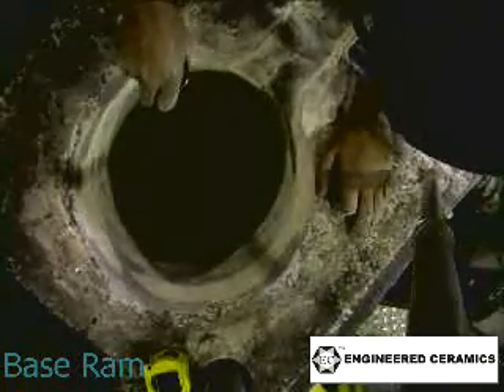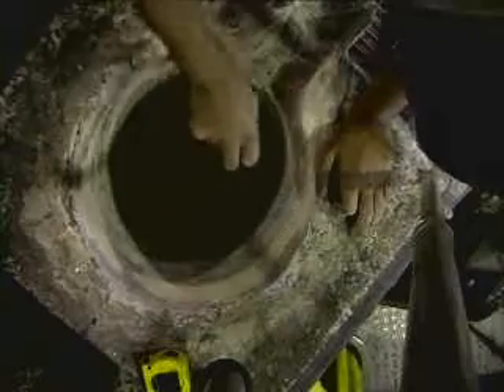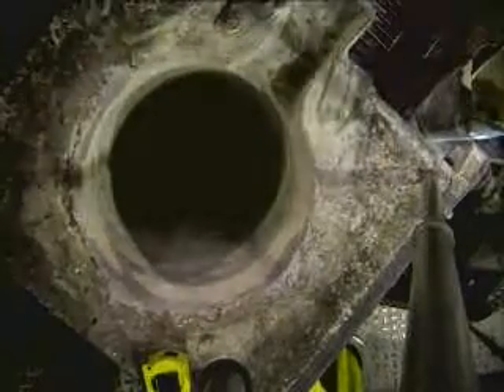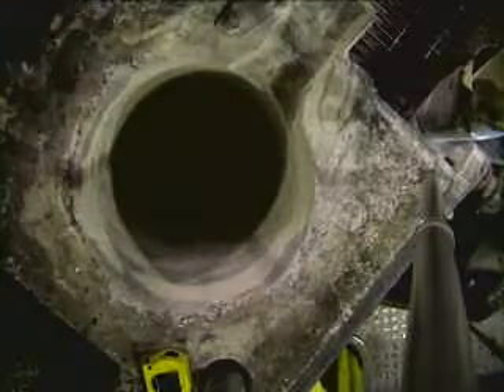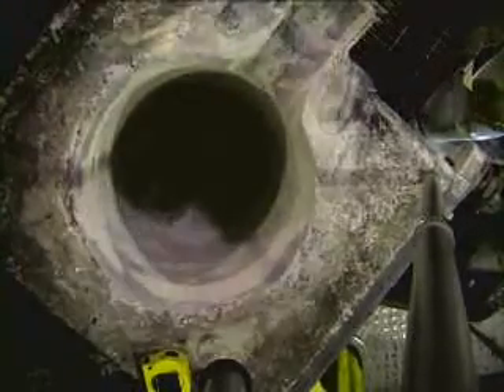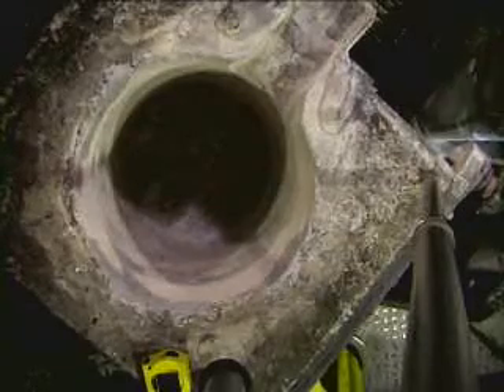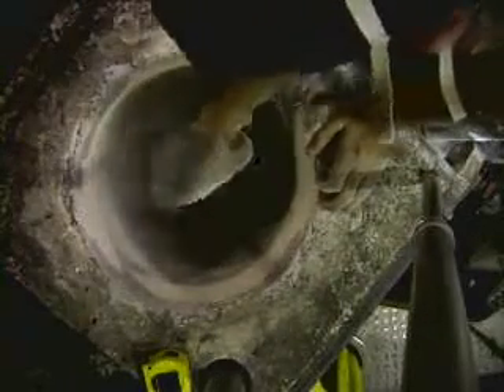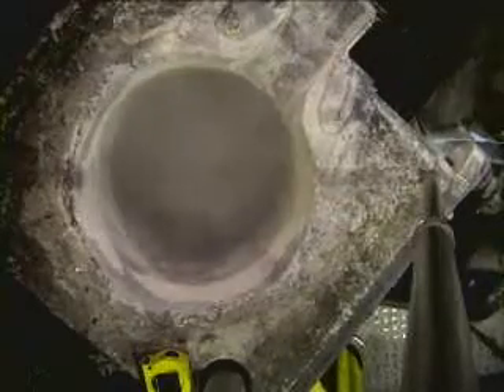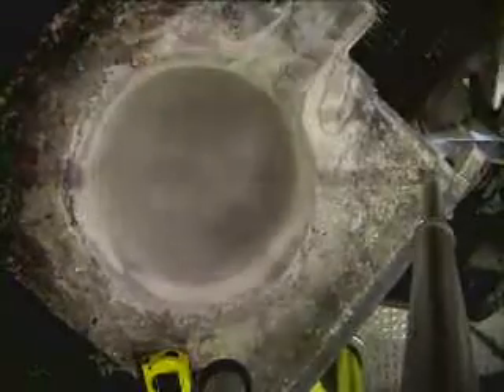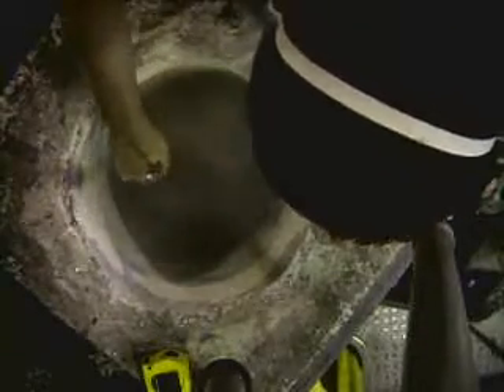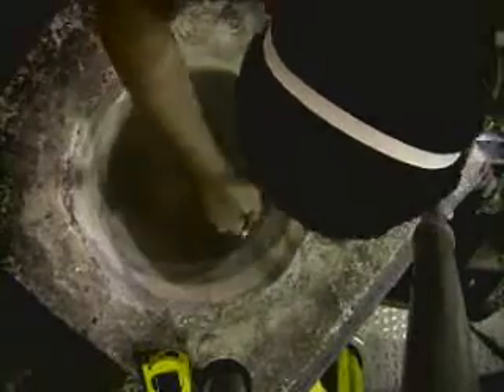Before adding the next layer, scratch the top surface of the ram. This promotes knitting between layers and prevents laminations, which can cause crucible failure. After scratching, add 1 to 2 inches of loose material and ram to a hard pack. If additional base ram thickness is required, scratch the top layer and continue until the required height is reached. The bottom of the crucible should roughly line up with the bottom of the furnace coil. At least 3 inches of base ram is recommended to provide support for the crucible.